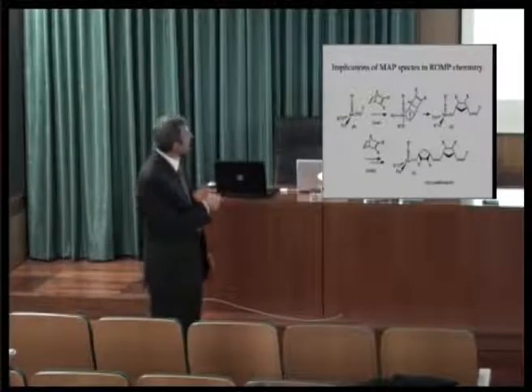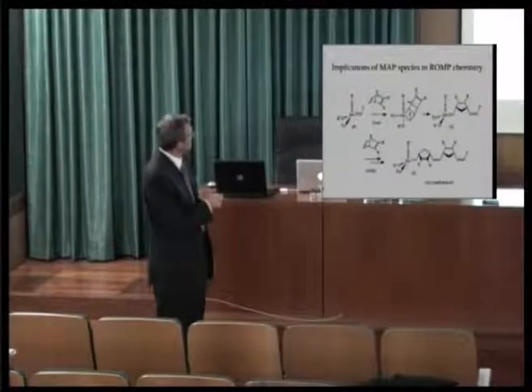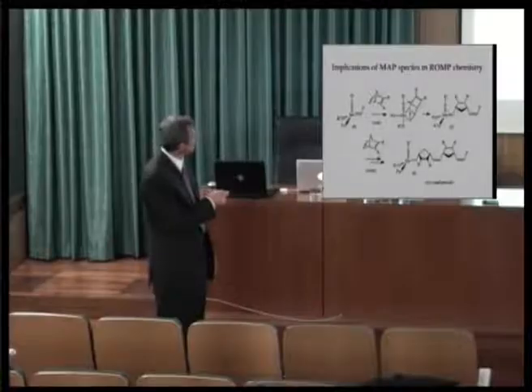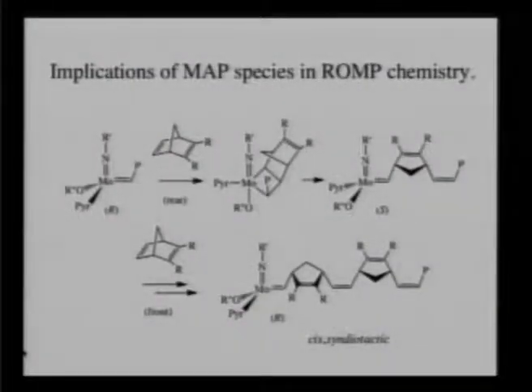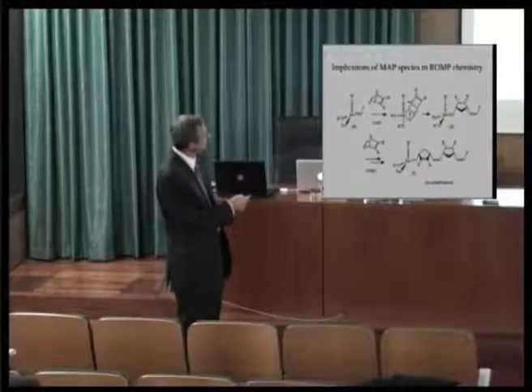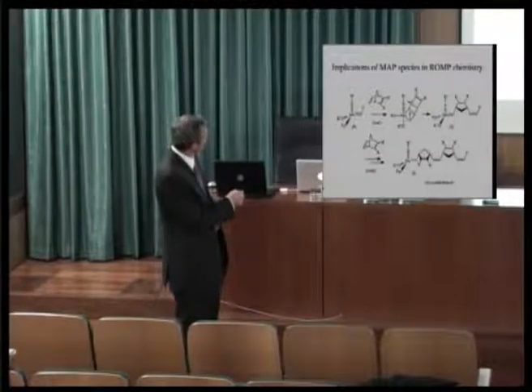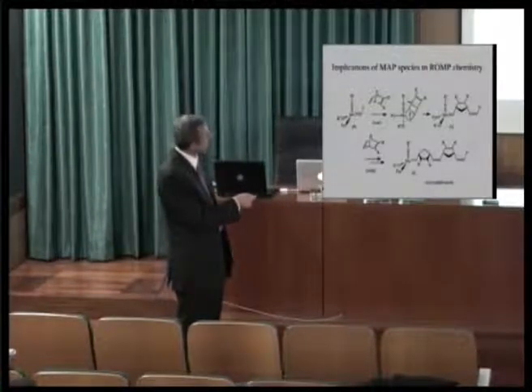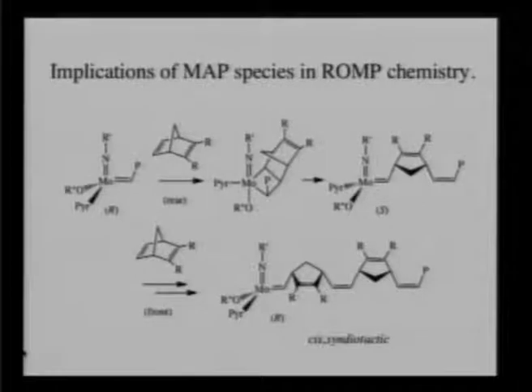Based on what is necessary in a reaction with these MAP species, we can predict that a monomer such as this, these are dicarbomethoxy norbornadienes, 2,3-disubstituted, must react, and again, I don't have time to go through the organometallic details because you probably aren't interested in those details anyway, in a way that gives rise to inversion of the metal with each insertion. And therefore, this monomer comes in trans to the pyrrolide from the back. And after one insertion, the next monomer comes in trans to the pyrrolide from the front. And you automatically get all cis or Z syndiotactic relationship between those two groups. And then the next one comes in like this one, pointing forward, back, forward, back.